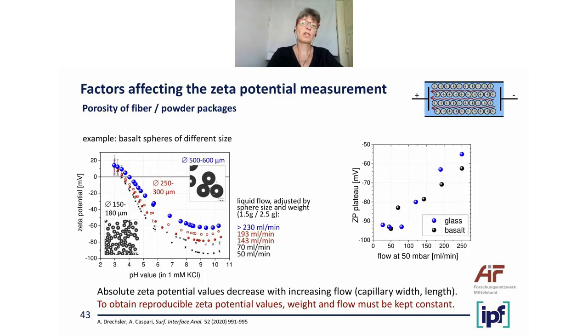If you measure the Zeta potential of fiber or powder packages by streaming potential measurements, as symbolized by the image at the top right, you also see an effect either of the size of the particle or of the weight you put into the measuring cell. It means the number of particles. And to study this, we measured the Zeta potential of basalt spheres of different size and of different weight or number of particles. And we measured the liquid flow through this particle package. The liquid flow is shown as numbers beside the left image.